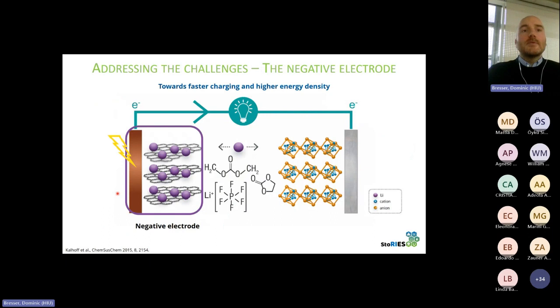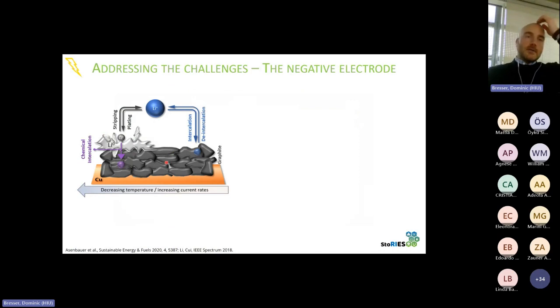So as said, when it's about the negative electrode, it's about faster charging and higher energy density. So we might briefly think about why fast charging is limited and why this is specifically related to the negative electrode. As you've seen earlier, graphite is a wonderful material because it operates at such low potential. But the drawback, nothing good comes without a drawback, is that it's very close to the redox potential of lithium. So when we apply high currents, so fast charging, or we do this at low temperatures, then we risk that we plate metallic lithium on top of the graphite electrode.